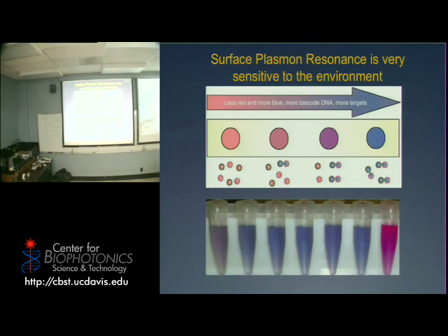So you can imagine developing assays like this, and there's a lot of stuff like this out there, where you have a particle like the ones circulating around, that are red, and then imagine adding on the surface some sort of receptor. It could be an antibody or an antigen. It could be a piece of DNA. And you have another set of particles labeled with the complementary, which could be the pathogen they're trying to detect. If you mix them together, if the test is positive, they start aggregating because they recognize each other, say the antigen recognizes your antibody. As they aggregate, not only do they become larger, but it also perturbs the plasmon resonance, and so they start changing color.